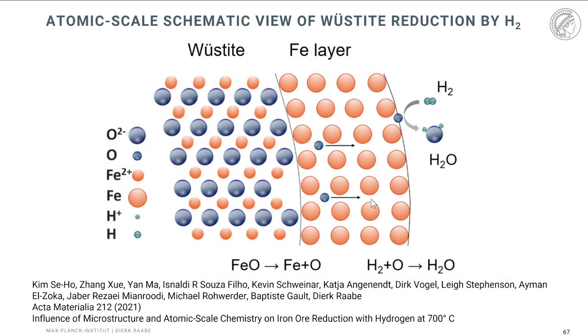This is shown schematically here. That means the oxygen from the wüstite must escape through that iron layer towards the surface, where it can recombine with hydrogen to form water. This is the current picture that we have about this process.